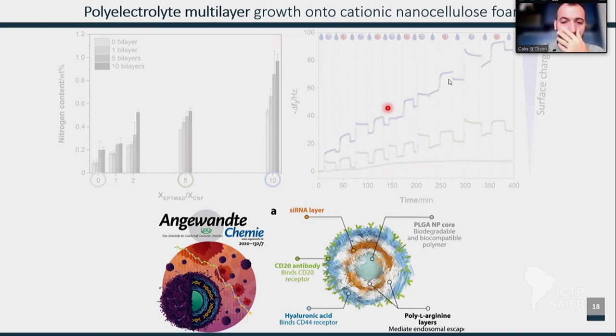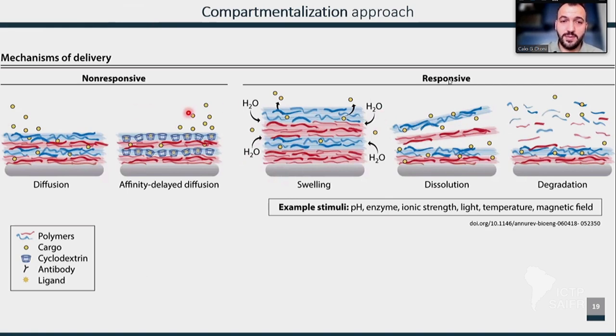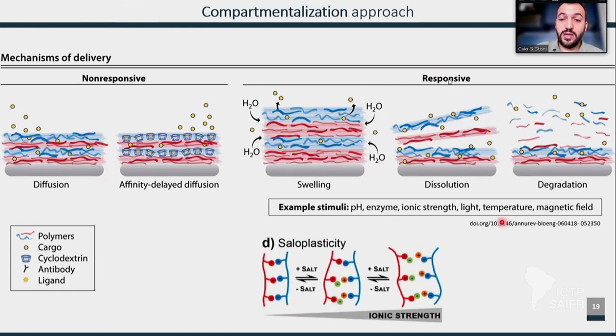She's in the bio field, and she works with growth factors, enzymes, RNA, drugs, whatever she wants to compartmentalize, she does using these layers, you know? And it's interesting because after you do this, you have to get rid of them, right? For release, or for growth factors to play their role, or for RNA to reach their targets, right? And you have different mechanisms for the delivery, either non-responsive or responsive. So talking about the responsive, you can swell the multilayers so the diffusional path is easier, smaller, less tortuous, right? You can have dissolution if the multilayers are water-soluble. You can have degradation, for instance, by enzymes or in the body, right? And I would like to mention again that we can reach this reversibility using salt, right? That's why the saloplasticity comes into play.